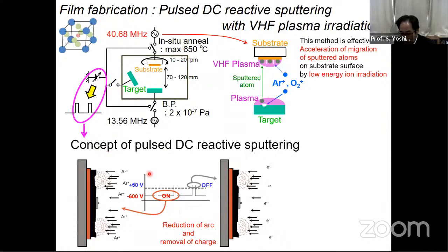In this system, we can generate minus voltage and plus voltage like this. In the case of minus voltage, a high sputtering phenomenon will occur. And in the case of plus voltage, electrons can remove the surface charge. So we can reduce the arc around the sputtering target.